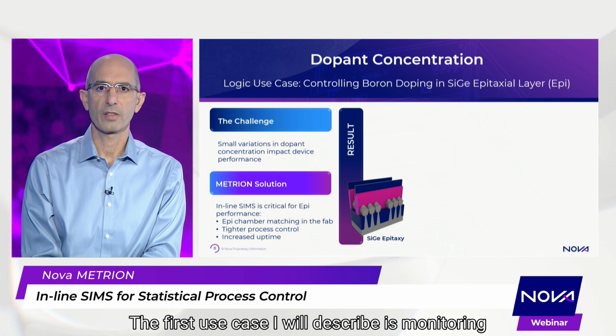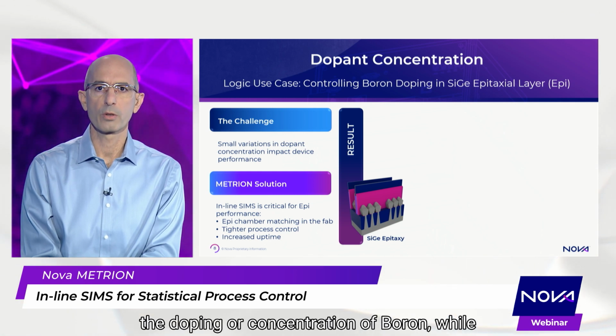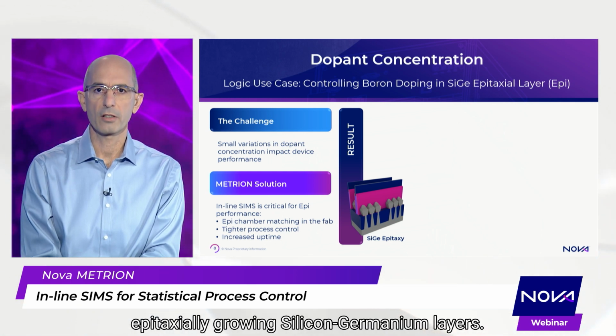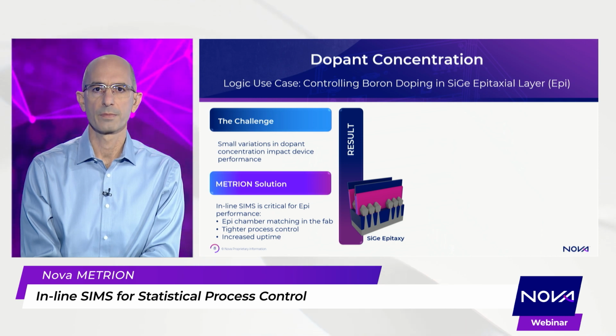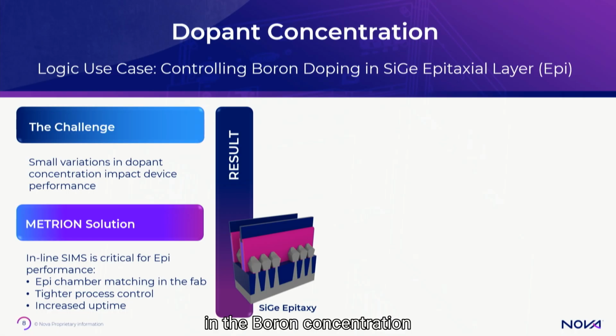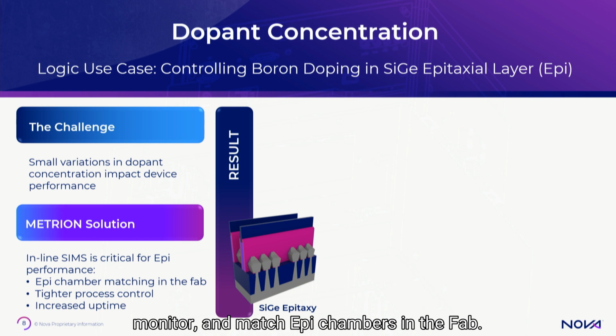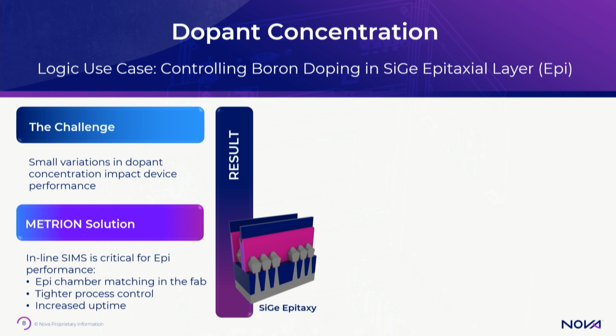The first use case I will describe is monitoring the doping concentration of boron while epitaxially growing silicon germanium layers. Since very small variation in the boron concentration can impact the final device performance, the METRION platform is used to qualify, monitor, and match epi chambers in the fab.